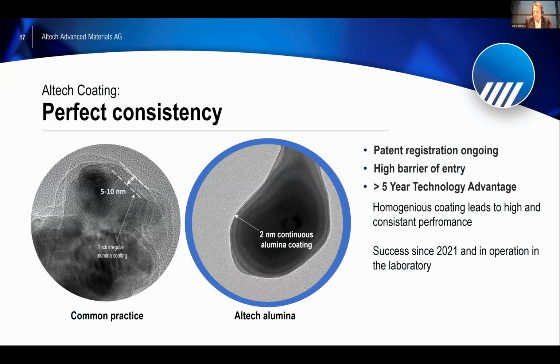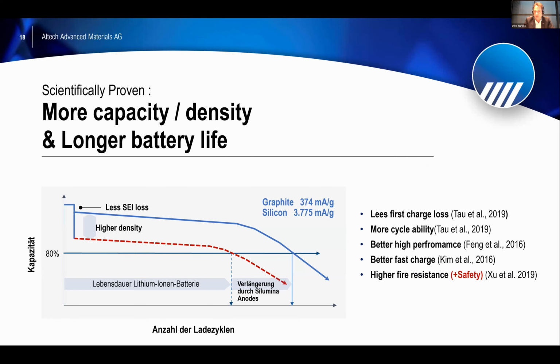And here, these are pictures of actual particles. You can see how others do it. Ours is very nice and homogeneous. Why is that important? It is important because otherwise alumina or ceramic becomes an isolator if it's too thick or not porous and so forth. And with this coating, you have more capacity, more density, longer battery life, everything.